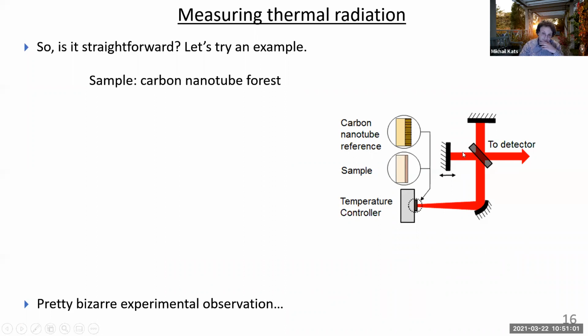So here's an example. What we did is we took a laboratory blackbody reference, which is a piece of silicon wafer with a vertically oriented carbon nanotube forest on top of it. Essentially, this forest is quite tall. It's about 500 microns, and this thing is more or less a good blackbody from the visible all the way to the far infrared, just because it's a very absorbing layer and it has this gradient index structure, so it's well impedance matched to air, so there's really no reflectance, and it's very, very black.